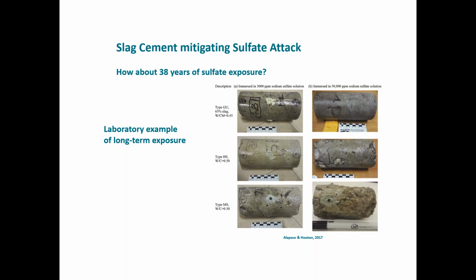I believe for this one it was like 11.5%. So it's very high by typical standards for general use cement. But what you see is that with 65% slag cement at a 0.45 water cement ratio, after 38 years in 2 different sulfate solutions, it's by far the best looking concrete.